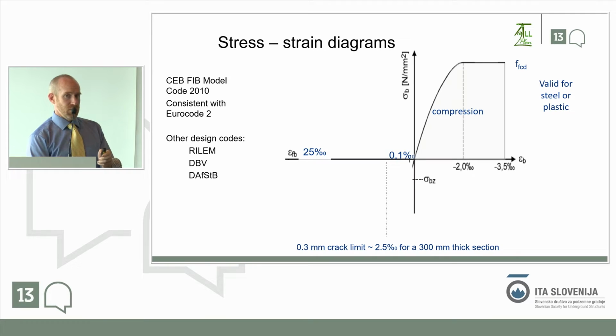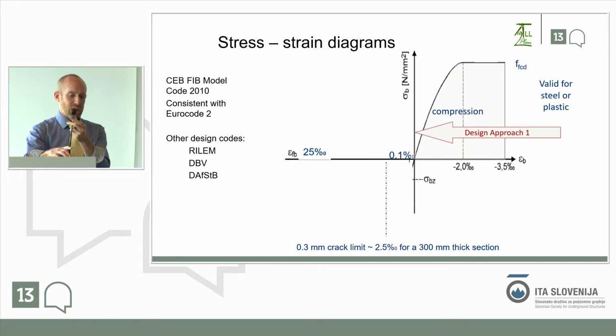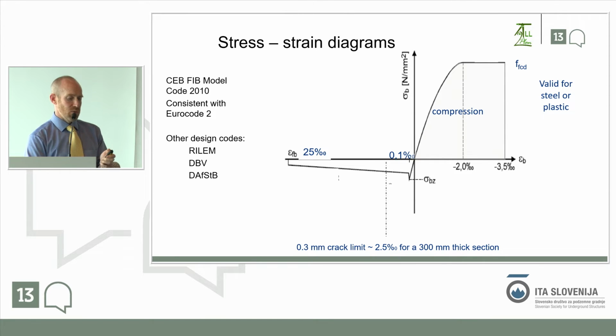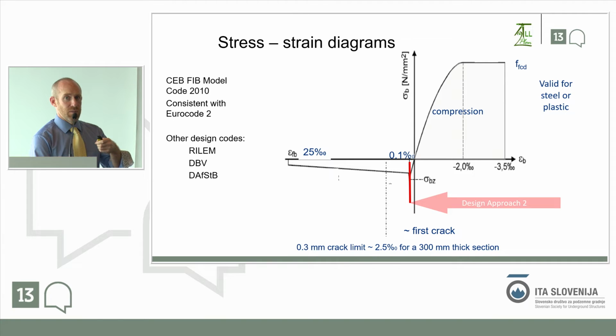So it's very durable. If we move on to design approaches, there are different ways of looking at that, but essentially, in my mind, we're adding the fibres to ensure that we have a ductile material. Plain concrete is brittle. With fibres, it's ductile. We get some bending strength, but if we've got big bending moments, we need to have bars. So that's the summary. People have looked at different ways of designing. Maybe they assume that there's zero tensile strength. That's very pessimistic. We know, and some of you may recognize this from the German guideline, that you have that peak, you have some sort of tensile capacity because we've put all these fibres in. So we need to make use of that. Just making use of the peak tensile strength of concrete, again, we're not gaining anything.